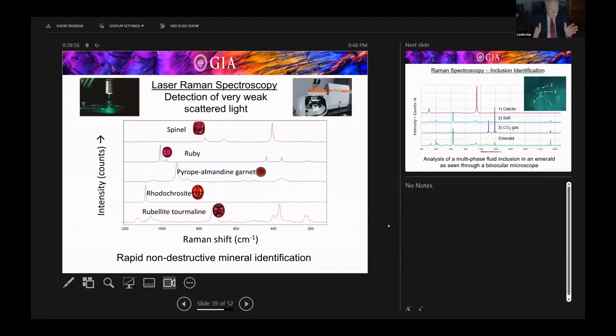Laser Raman spectroscopy is a really important technique. You have a laser that's aligned along the optics of a microscope. It is a very rapid method of doing mineral identification. And just as an example, I show a group of red stones. It just takes a few minutes to record a Raman spectrum. I've even seen at the mineral shows, we have a big one coming up here in a few weeks in Tucson, little handheld Raman units that people are using walking around the mineral show. And if you have a database, you can identify minerals quite quickly just by pointing this device at the sample and getting a Raman spectrum.